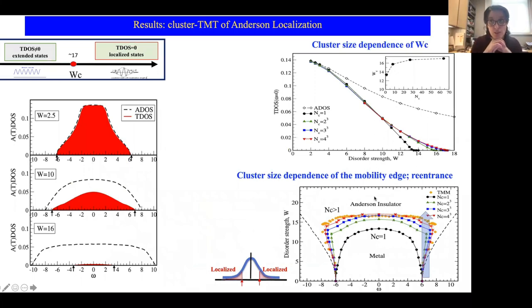When I calculate the typical density of states, it's not the actual density of states. So if I calculate density by integrating this density of electrons, it's not going to give me the true density of electrons. This is just machinery to identify either mobility edges or whether the system is localized or not. When applying this approach to real materials, one also has to be careful, because if you want to do a charge self-consistency loop, you have to make sure that you calculate the actual density of states and not the one obtained from the typical density of states. Okay.